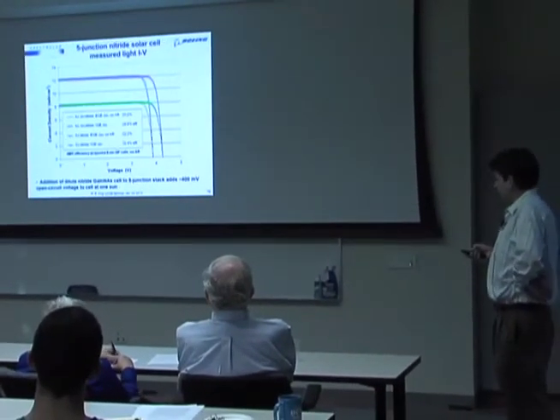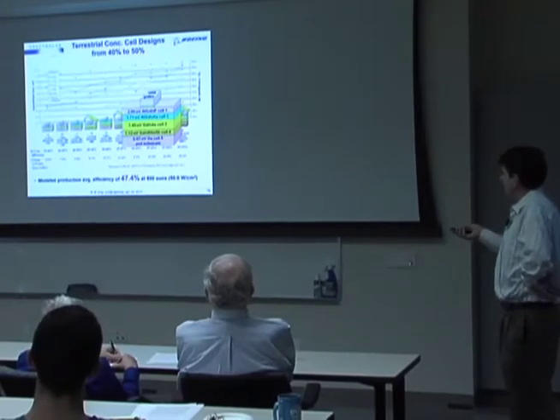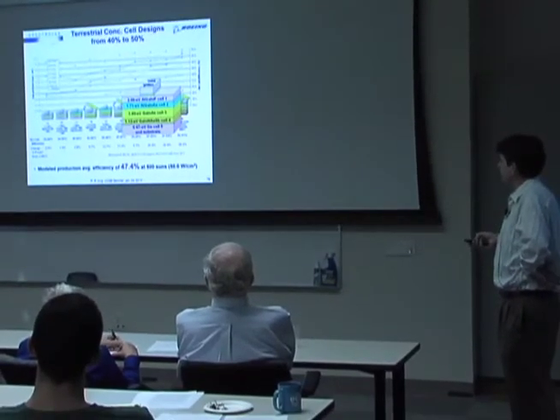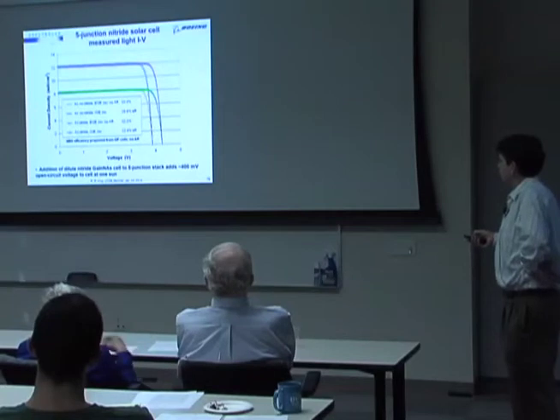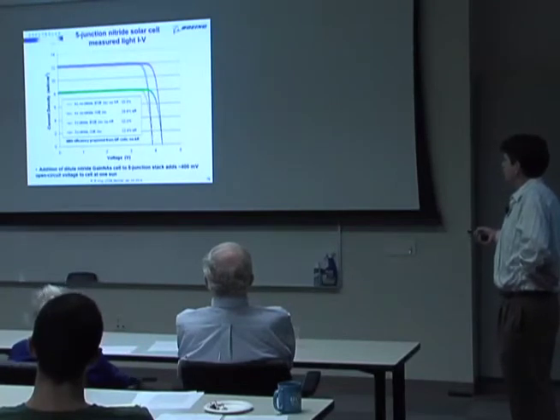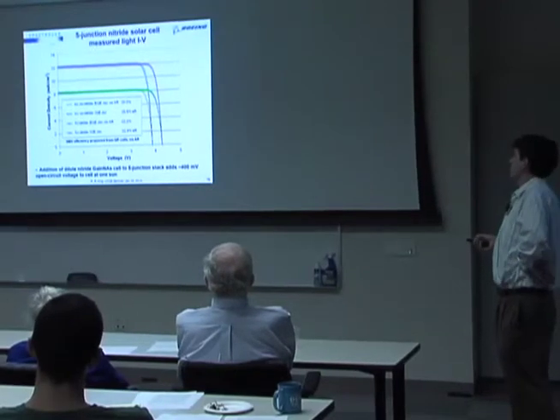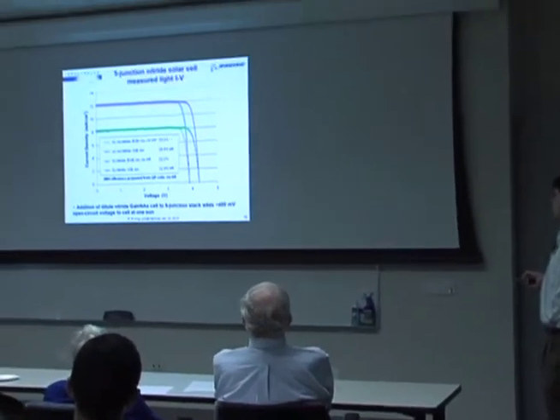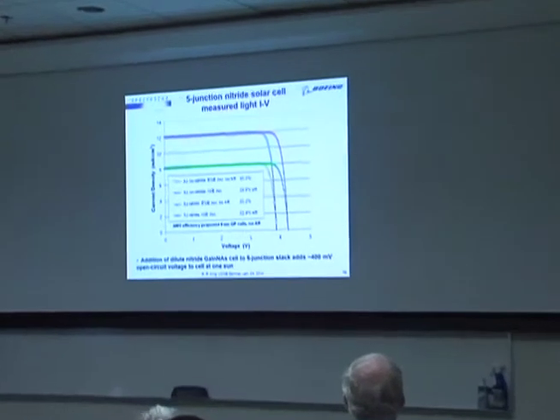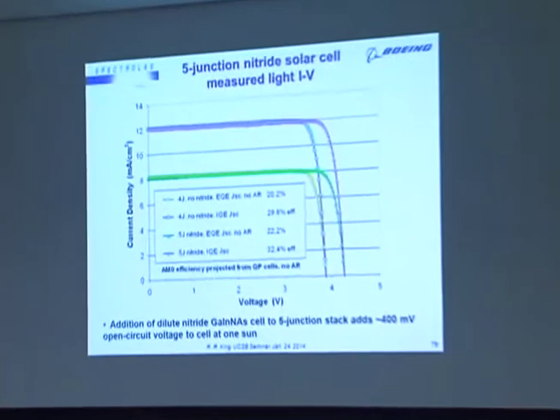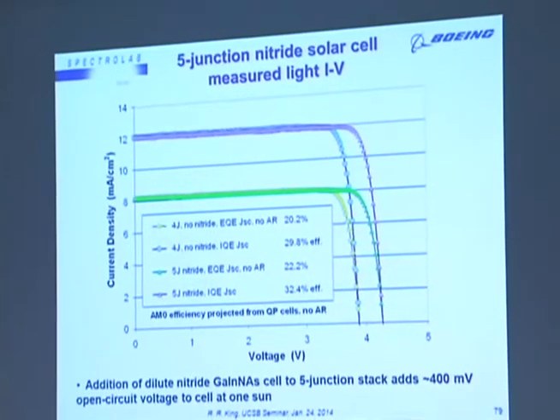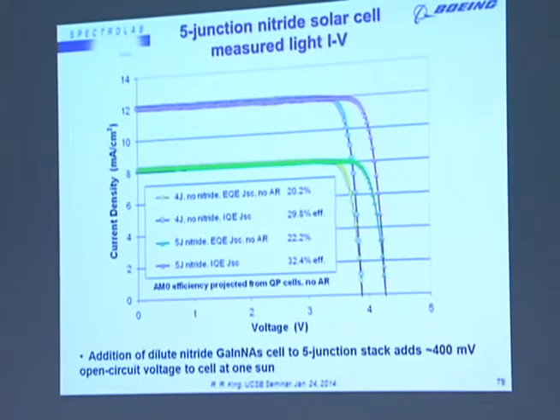Some other results on the 5-junction gallium indium nitride arsenide cell that we looked at in schematic before is shown here. These are 4-junction cells, IV curves going out to a little bit less than 4 volts. The addition of a nitride cell to form 5-junction cells is very reproducibly showing the increase in voltage that one would expect of about 400 millivolts.